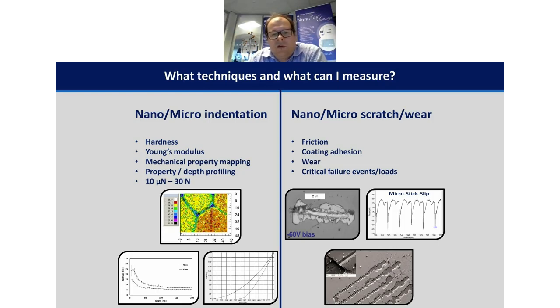Importantly, also for coatings and for bulk materials, is tribology. So we move into nano and micro scratch and wear testing. This enables us to look at properties like friction and the adhesion of coatings to surfaces. It's one thing to develop a high performance coating, but it's another thing sometimes to achieve good adhesion of that coating to the substrate, and without that adhesion, the coating property is compromised in what it can offer in an engineering system.